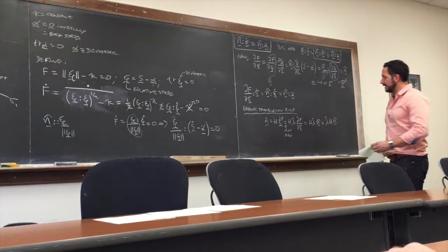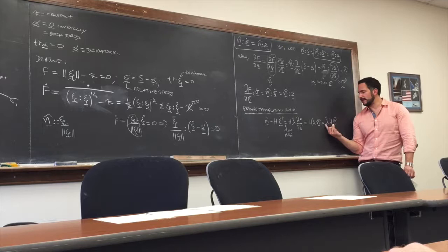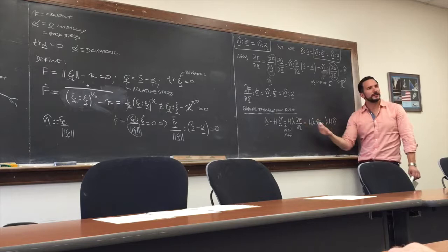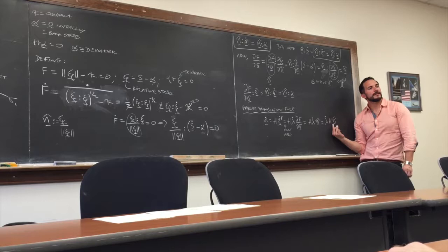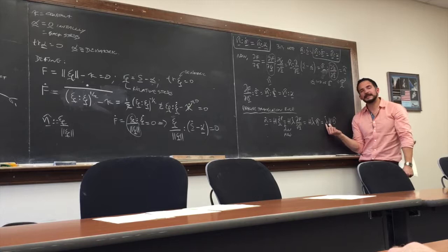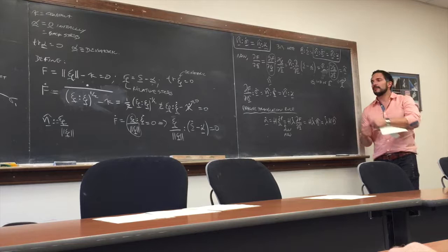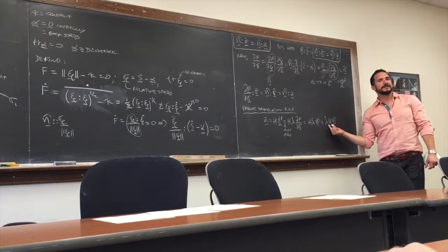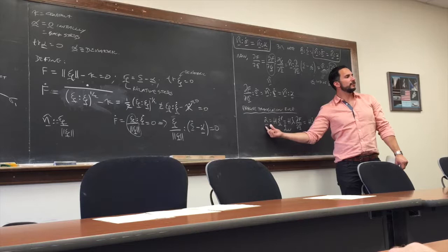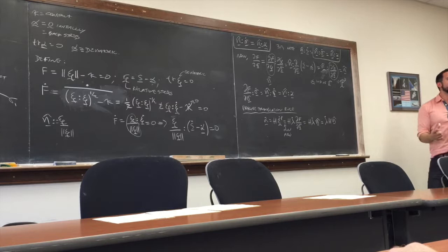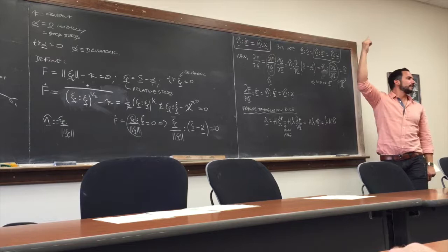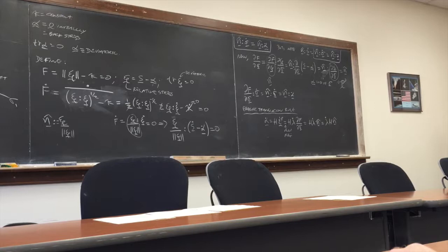It doesn't really matter. So again, I like to think of vectors, and this gives me the magnitude of the vector change in alpha. And this always gives me the direction. This points in the direction, and then this scales it. The more plasticity I have, the more plastic strain I have, the more alpha dot I need to have. Also the higher H is, the bigger this is going to be. As H approaches zero, perfect plasticity, it's harder for alpha to change, to move. You go back to a static, rigid cylinder that doesn't want to go anywhere. The more plasticity you have, the more that cylinder has to move. Think about it. There are all these geometric interpretations of all these things.